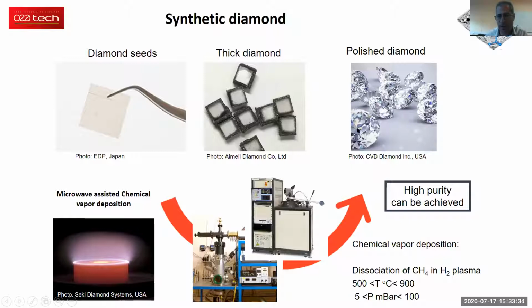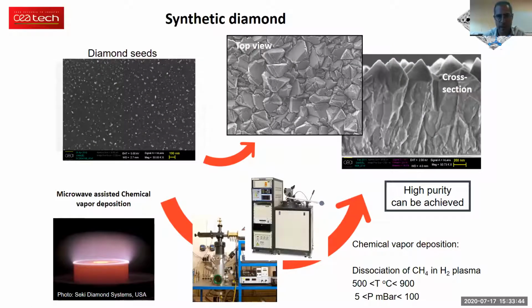If we polish it, we can get some very nice diamond crystals like these. They're beautiful, but they're not very useful for making sensors. So an alternative is to deposit some diamond nanoparticles over, for instance, a silicon substrate. They look like these. These little dots here are nanodiamonds. They are typically between 5 and 20 nanometers in size. And as we grow these nanoparticles in the same reactor, in the same conditions, this is what we get at the end, a thin film of polycrystalline diamond. And this is a lot better for us for sensing applications.